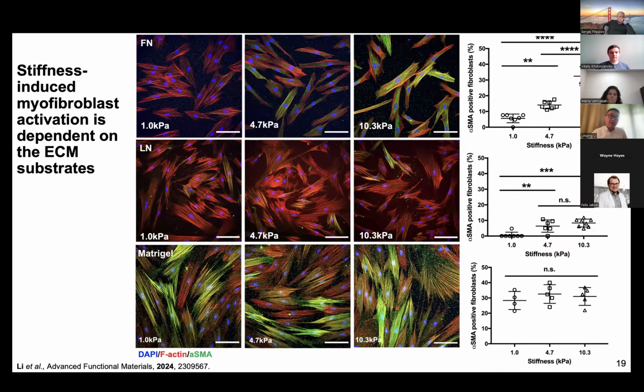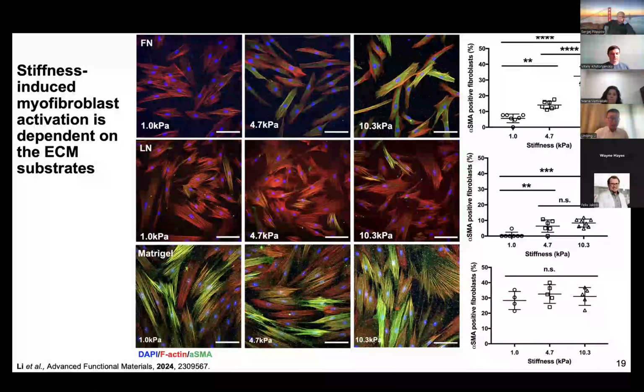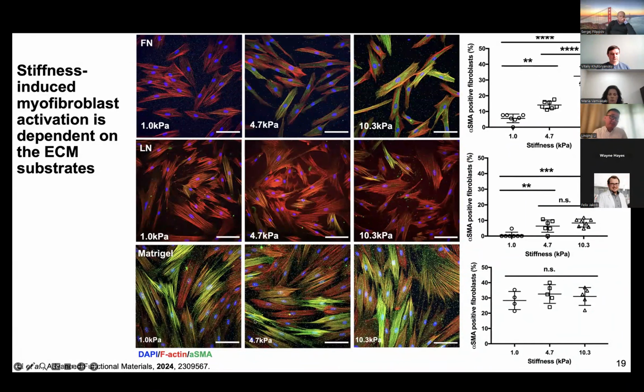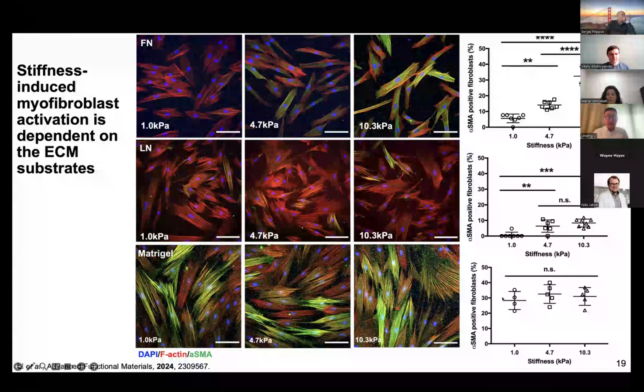So now this shows us that by changing the substrate, how cells are sensing, you can actually control and dial down that activation of the fibroblast. Then again, we choose another protein we're looking at, Matrigel. Now this is the other end: by Matrigel coating, regardless of the stiffness, even in the softer substrates, you have consistently a high percentage of smooth muscle actin positive cells that have been activated.